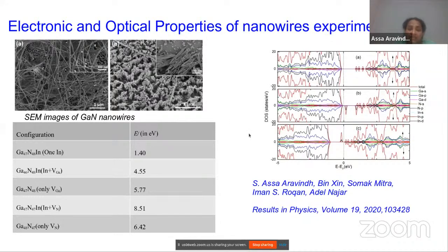So we can easily introduce defects in our calculations. So we have done it with point defects and also complex defects such as a dopant and point defect, which has shown very high stability in the material. And also we could see that the electronic structure is altering.